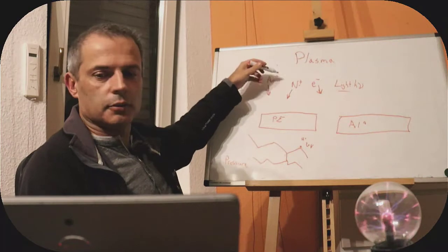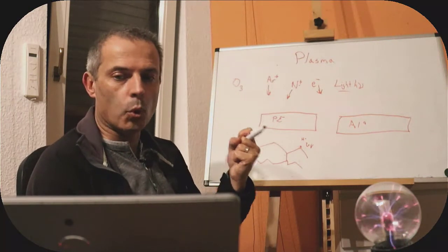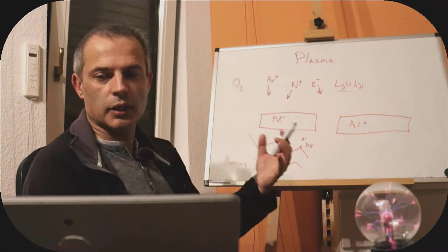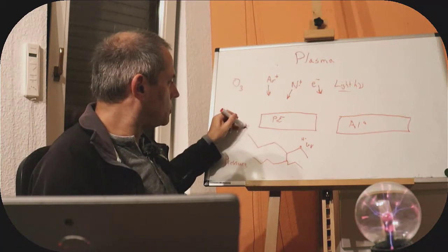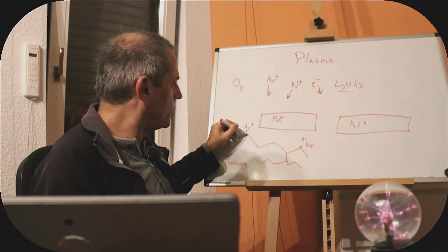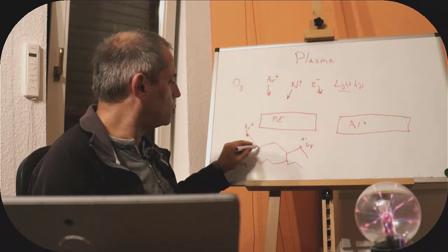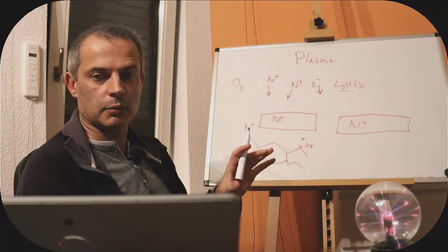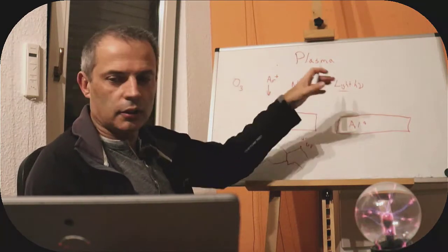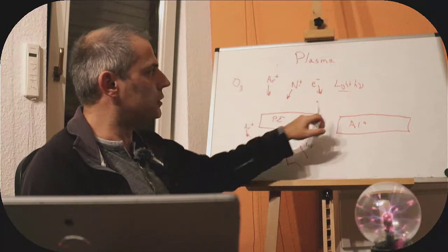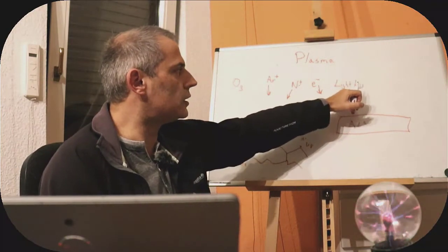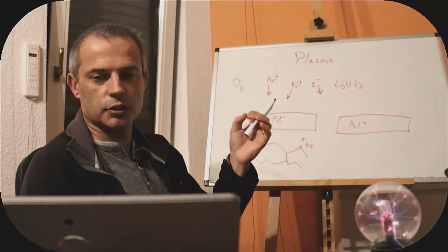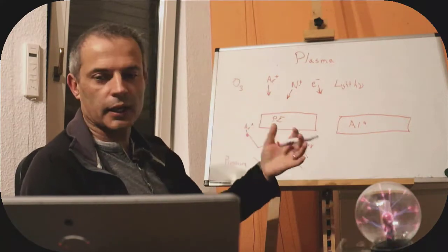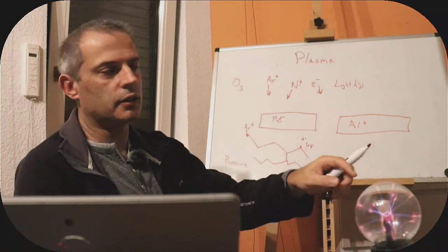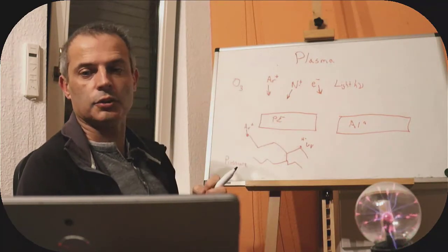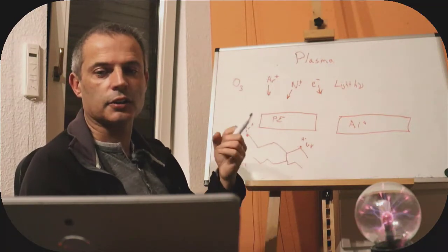The argon ion, which is the next most complicated one, can come in, and that's got more energy because it's heavier, and so it can ballistically knock stuff out, maybe knocking this whole methyl group off the end, leaving a broken bond and causing a similar effect to the UV, but chemically somewhat differently. It can also go into the bulk material, but it has a different depth sensitivity to ultraviolet, which will be absorbed close to the surface, because ultraviolet, if it's short-wave enough, will be absorbed by anything, but it can pass through quite a bit. The argon ions can punch right into the surface depending on how much voltage we've given them, so what the voltage and pressure are, how much chance we've given it to accelerate.